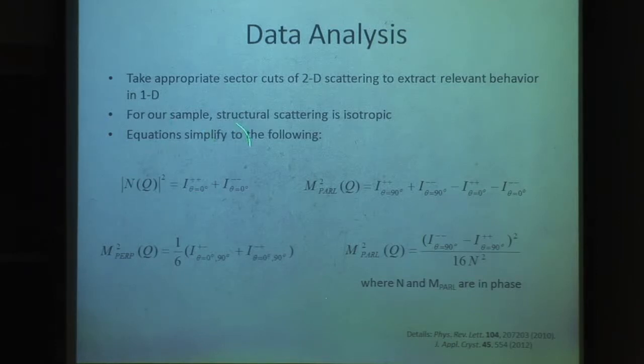We have N squared, which is our structural scattering, dependent only on our up-up and our down-down scattering, and is proportional to our intensity. Our perpendicular scattering is proportional to our up-downs and our down-ups, our spin-flip scattering, because we're flipping what direction the spin was in between. And then we had 2 relevant equations for our parallel scattering, one of which was completely independent of any other equations. Our other one was dependent on our structural scattering.